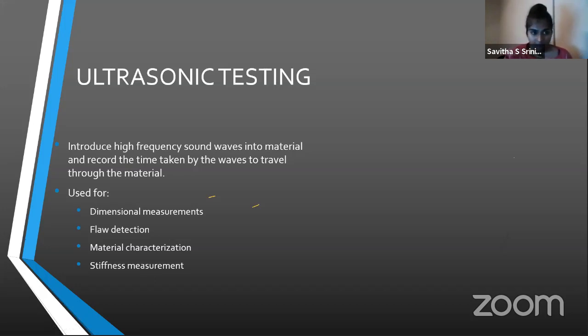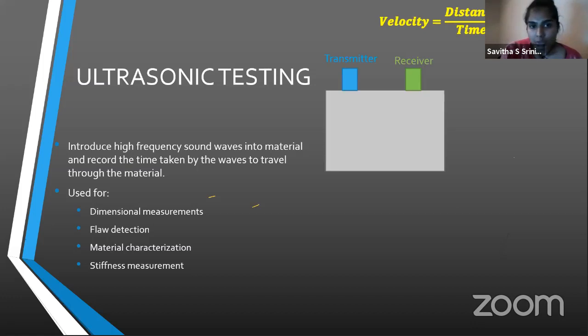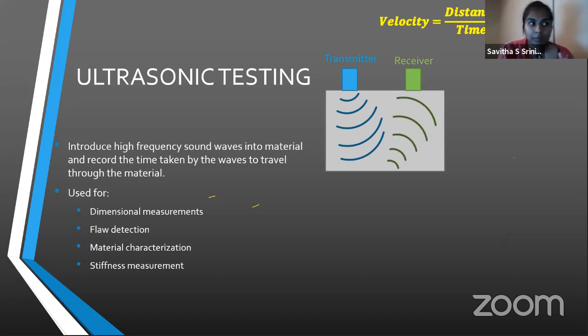The next one is ultrasonic testing. So ultrasonic testing is basically you introduce a high frequency sound wave into a material and then record the time that's taken by these waves to travel through the material. Basically, velocity is distance by time. So you can use it for dimensional measurements. Say you have a concrete specimen, you have a transmitter, which will send out a pulse, and then that bounces off the edge of the concrete specimen and will be received.